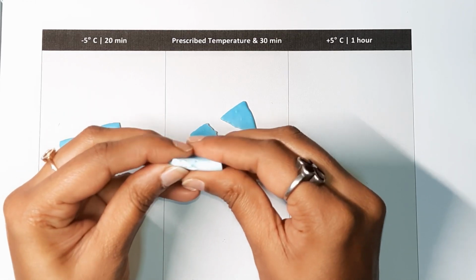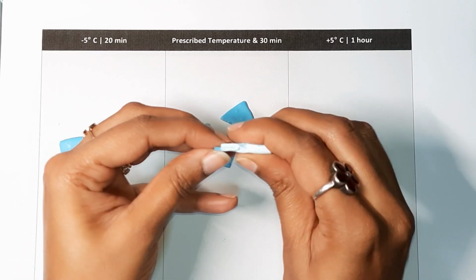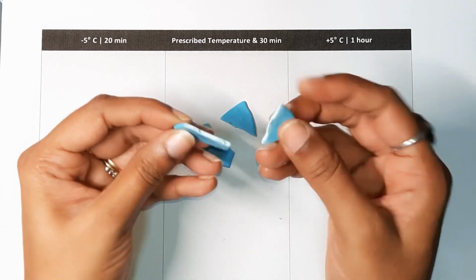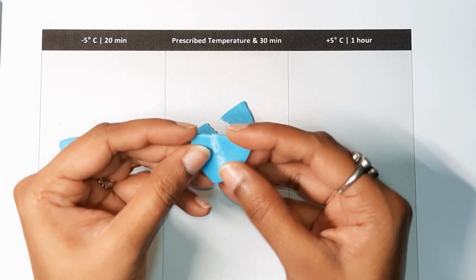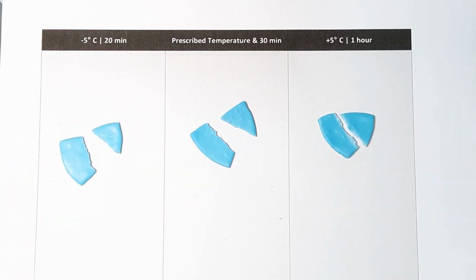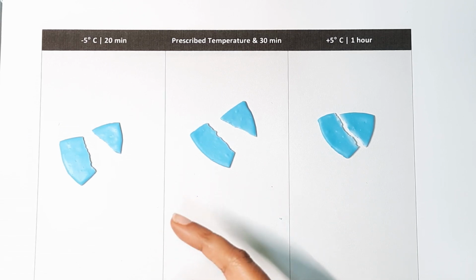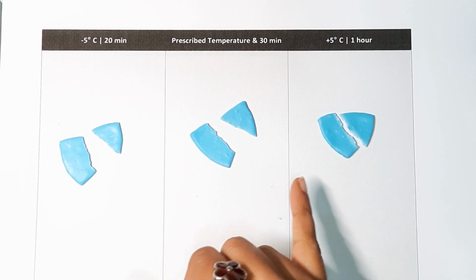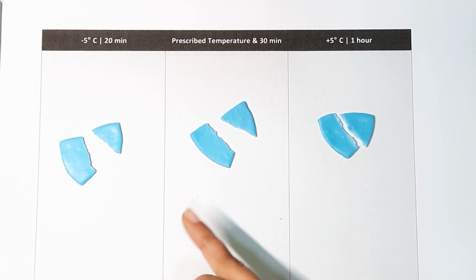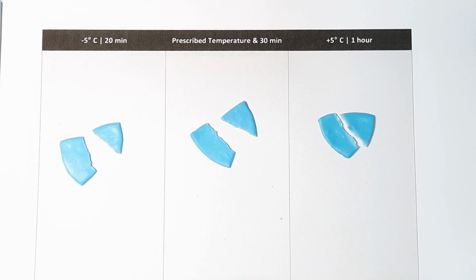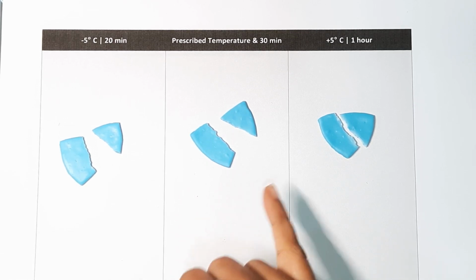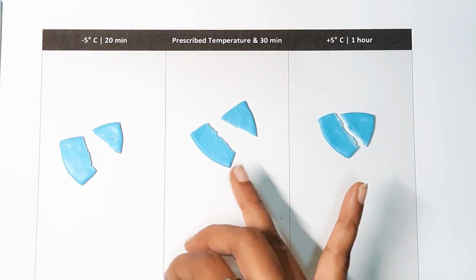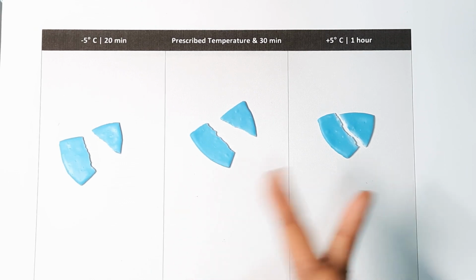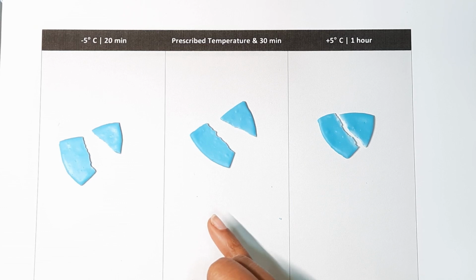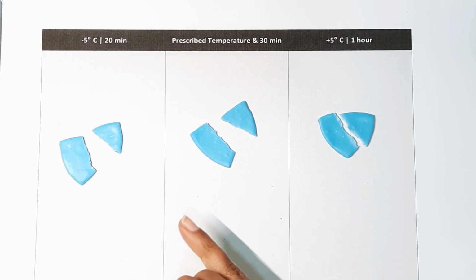It tends to hold far stronger, but it's still not as strong as it should be. It still tends to tear, and I can break it. Yes. There is a bit of resistance, but it still breaks. So yeah, that is the verdict on the basic polymer clay by Oytra. This one has not really lived up to the prescribed baking temperature and time, and the strength and flexibility are also not quite up to the mark. So I'm assuming that if you bake this at the prescribed temperature for probably an hour and a half, it might cure properly, but I'm not counting on that. I might have to think again about how to maintain the strength of this particular clay.